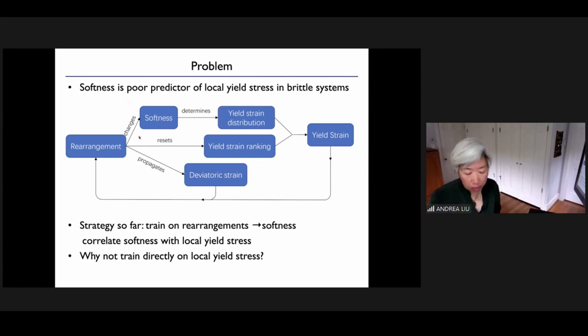But then we ran into an immediate problem, which is that softness turns out to be a very poor predictor of local yield stress in brittle systems. So our strategy was that we would train on rearrangements. We would give the machine learning algorithm particles that were going to rearrange, and particles that had not rearranged for a very long time and were not going to rearrange for a long time. And from that, we obtained the structural quantity softness. And then we found that the softness actually did correlate with the local yield stress. But that doesn't work in brittle systems.